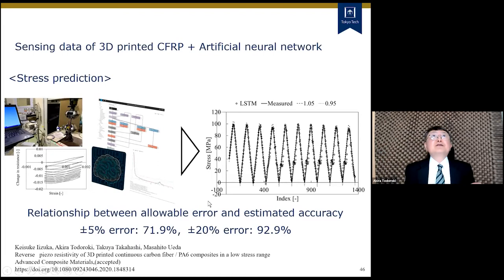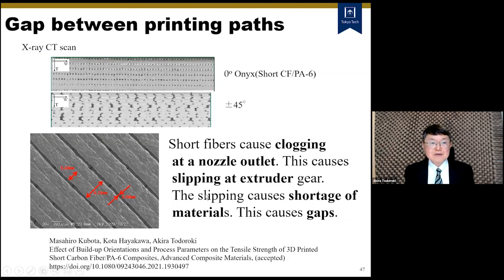I'd like to omit this because I don't have enough time. So this slide showed another research work. Even for the Markforged, we checked the infill print path, and we found this large gap between the print paths. And this was caused by short carbon fibers clogging the nozzle outlet.